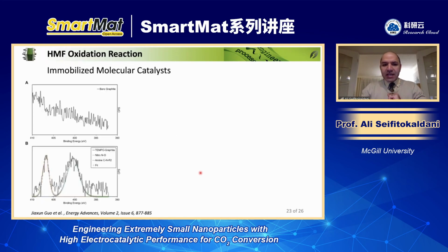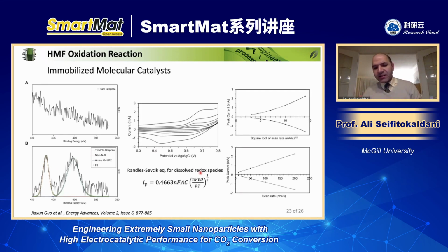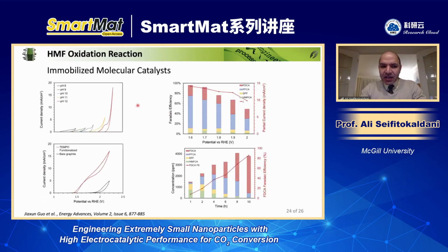So long story short, we also went through some sorts of characterization, for example, XPS or some pure electrochemical theory to confirm that our TEMPO is immobilized on the surface. And after that, we utilized it. As you see here, we were able to work under different pH from pH 8, 9, 10, 11, 12. These are just shifted to show them better. Otherwise, they all are at the same potential range. So you see that, of course, by increasing the pH, the current density increases, but then you also promote further oxygen evolution reaction.